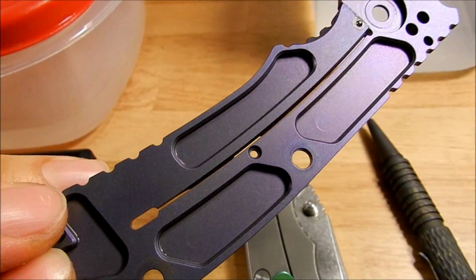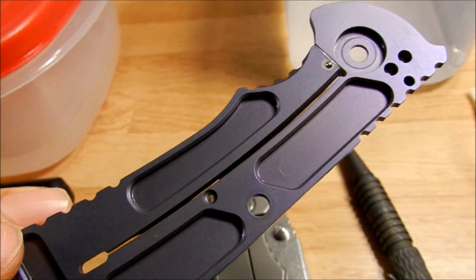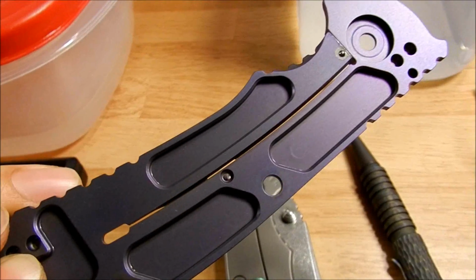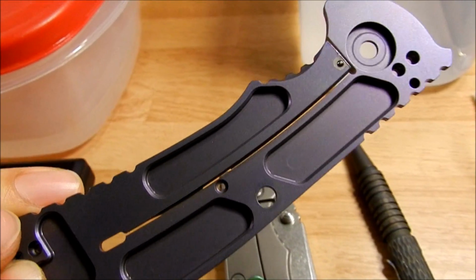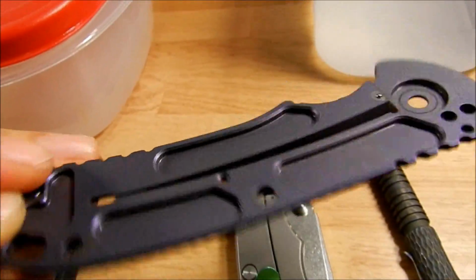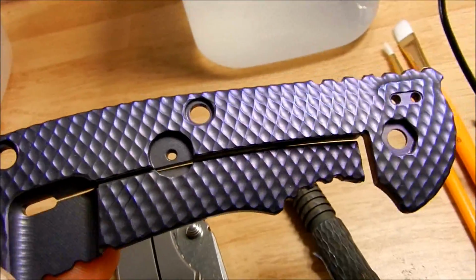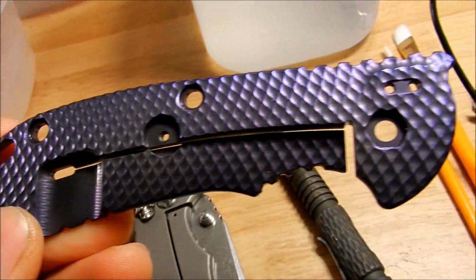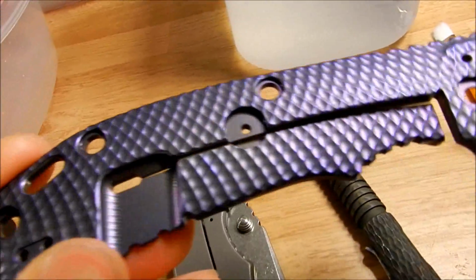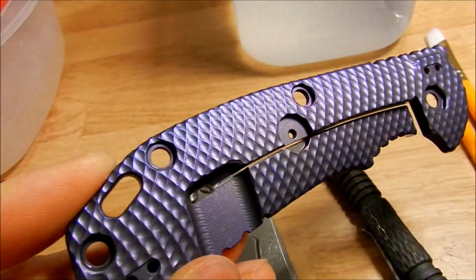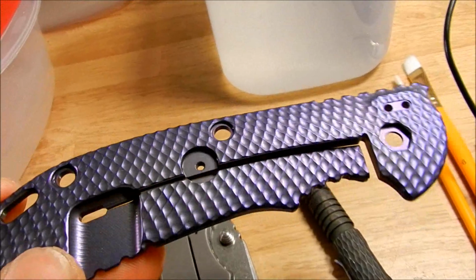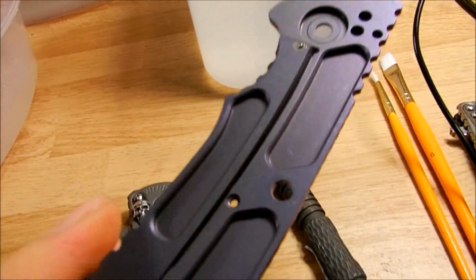Like on the inside, that's not blue at all. It's very cloudy. Now what I'm going to go ahead and do is scrub this with a toothbrush and see if I can remove some of that cloudiness. Alright, scrubbing it with a toothbrush has revealed a more vibrant color, but still very cloudy and not uniform. So I'm going to go ahead and dip this in the multi-etch and re-anodize it and show you what it looks like.